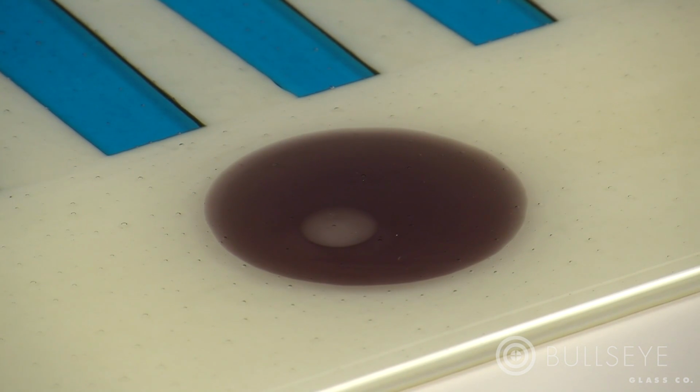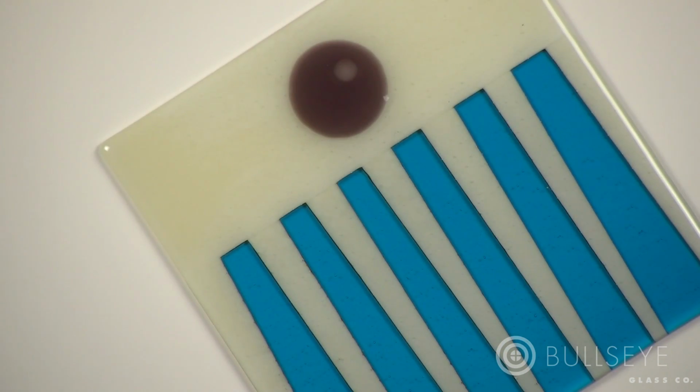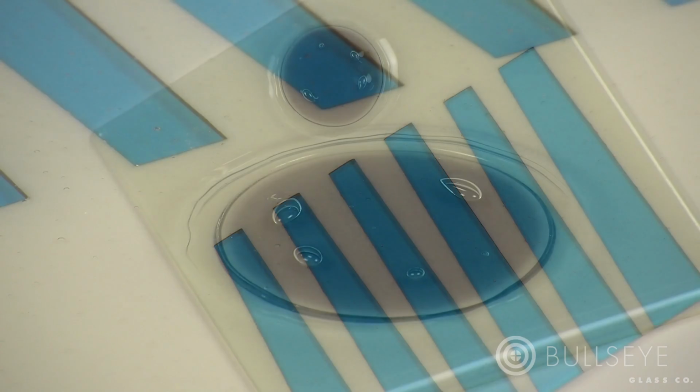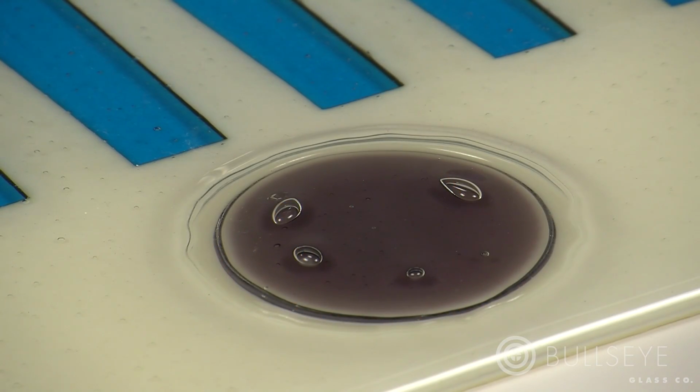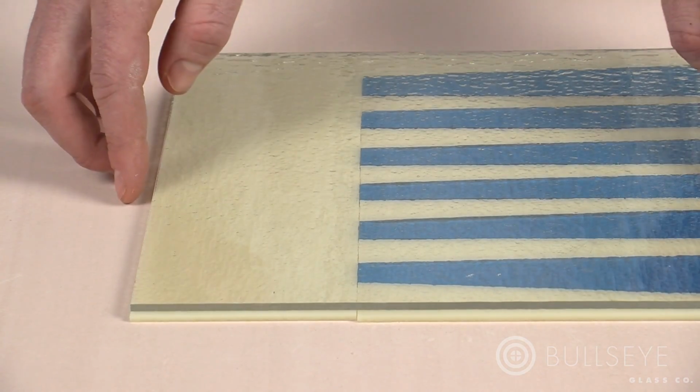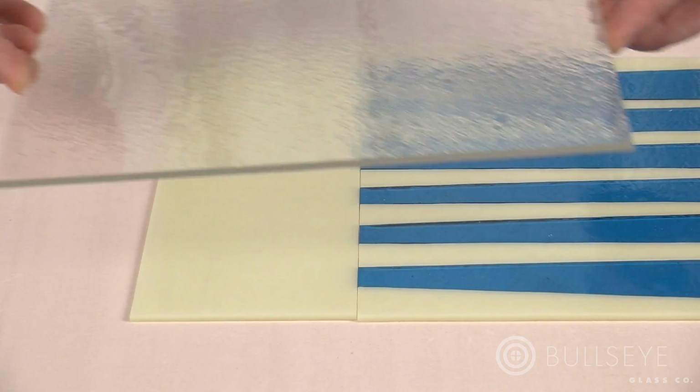Proper design and firing methods will result in small, champagne bubbles between glass layers. Such bubbles are accepted as part of the handcrafted glass aesthetic. However, it is possible to unintentionally create other types of bubbles that may be large enough to rise and disturb the top surface. To maintain control over both bubbles and volume, always work in complete layers.